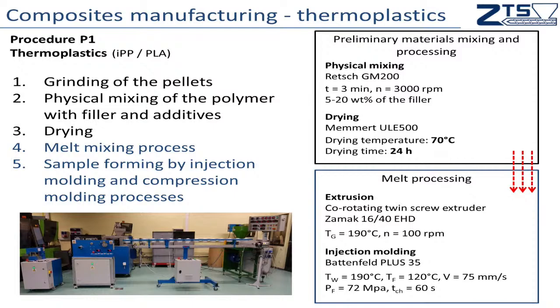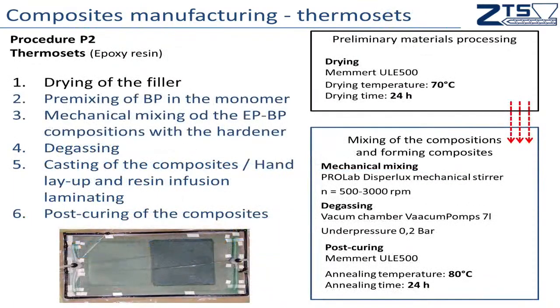In the case of all the thermoplastic materials, we make a preliminary mixing of the filler that can be realized by a gravimetric feeding system in commercial machines. Of course, all materials were dried before mixing in the molten state, and then we prepare the compositions with a twin screw extruder and form the samples using a hydraulic injection molding machine with the parameters as presented in the slide.